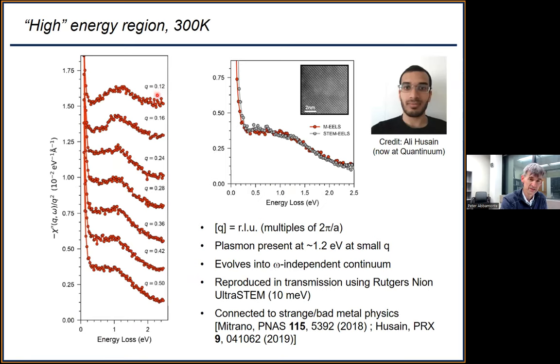So Q in this talk is going to be specified in what are called reciprocal lattice units. So what that means is, if I take one over the value of Q, that corresponds to the wavelength of the excitation in lattice parameters. So Q of 0.12 is an 8 lattice parameter period. Q of 0.5 is a 2 lattice parameter period. So these are sort of neutron scattering units. At any rate, this is low momentum. And as you march out, you can see what happens.